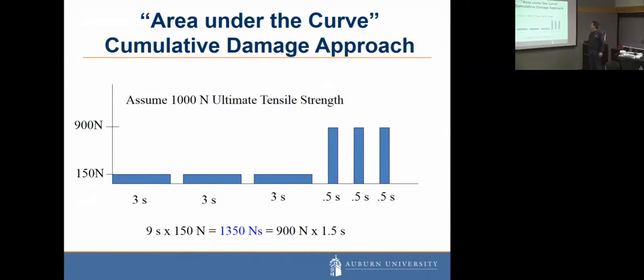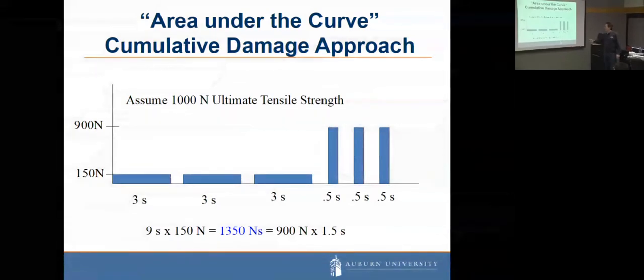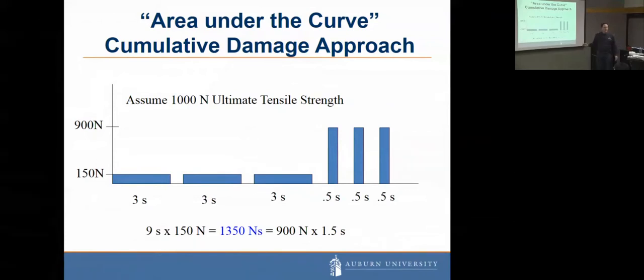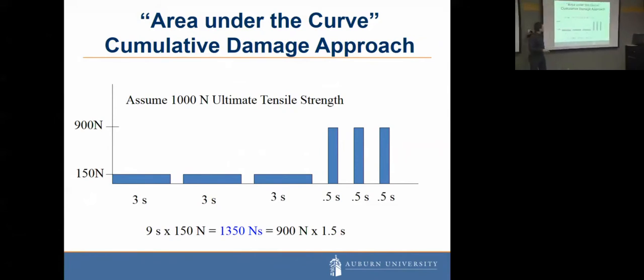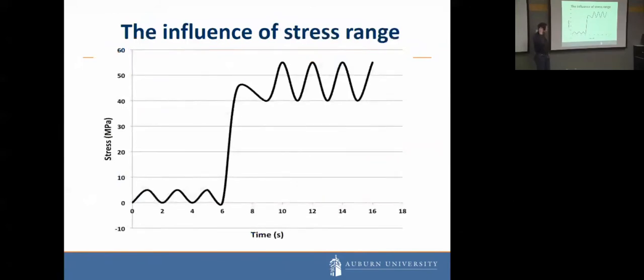But at that level, you can probably only do about 15 or 20 cycles before failure in this situation. And you could probably do hundreds of thousands or millions of those before failure. So we don't really think this area under the curve idea is very good in terms of getting a cumulative damage. The Palmgren-Miner rule, we think, does a lot better.